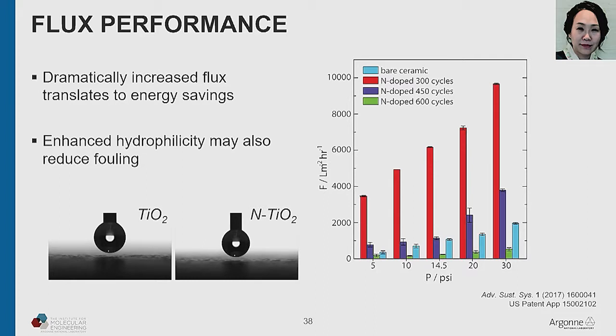And you can see in these dynamic contact angle videos why that happens. So here we take two of these membranes. One we do ALD of titanium dioxide, not doped. And the other one we do the same number of cycles of doped titanium dioxide. So they've been constricted the same amount. And it was the same membrane to start with. You can see when you put it on regular old titanium dioxide, that droplet of water does get imbibed into the membrane, but it takes, I don't know, 10 or 15 seconds for a droplet that size to be pulled into the membrane. You'll see the contrast on the doped one here. So we've made this thing super hydrophilic with this nitrogen doping.